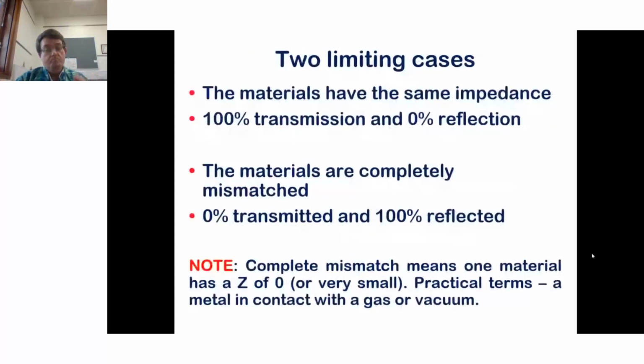Now, there are 2 limiting cases. Two materials have exactly the same impedance. That implies that you get 100% transmission of stress through the interface and 0 energy reflected. Or the materials are completely mismatched, meaning one of them has either infinite or 0 acoustic impedance, an extreme limit. In that case, 0 energy is transmitted and it's all reflected back at you.